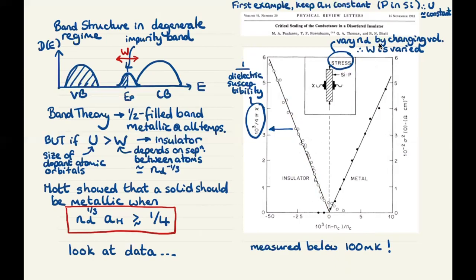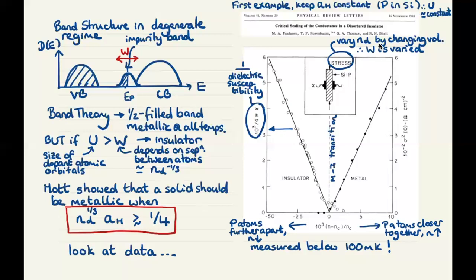The x-axis is the doping concentration measured relative to the critical doping concentration between the insulator and the metallic regime. And so in the direction to the left, the phosphorus atoms are moved further apart, and N goes down. And going to the right, the phosphorus atoms are closer together, and the doping concentration is going up. And the dashed vertical line is indicating the transition between the insulating and the metallic regime. On the right-hand axis is plotted the conductivity.